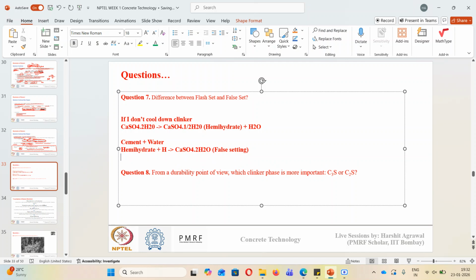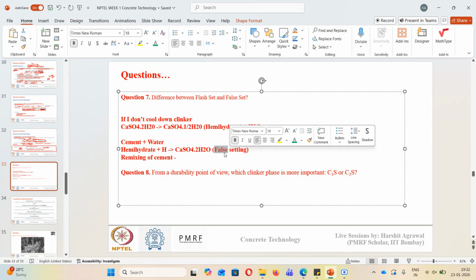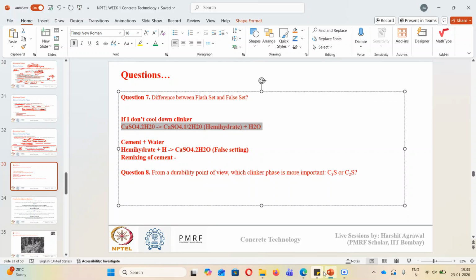mix, if we again do remixing of cement without addition of water, then this gypsum will again break into hemihydrate and water. So it will appear to be set, but upon remixing it will again become free. That's why it is known as false setting. False setting comes because hemihydrate converts into gypsum. That's why we say that before addition of gypsum to clinker, clinker needs to be cooled down so that this reaction doesn't occur. Everyone clear with the concept of false setting?